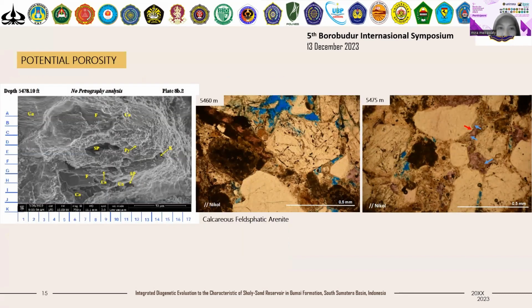And then here are some examples of the secondary porosity that we can see in the sandstone of Gumai Formation. The left picture is a photomicrograph of the scanning electron microscope, and the fabric porosity or the secondary porosity, as we can see in this section, is symbolized with SP, and the other we can see the porosity occurring in this blue part of the rock. And the irregular shape indicates it comes from dissolution as a result of diagenetic process.